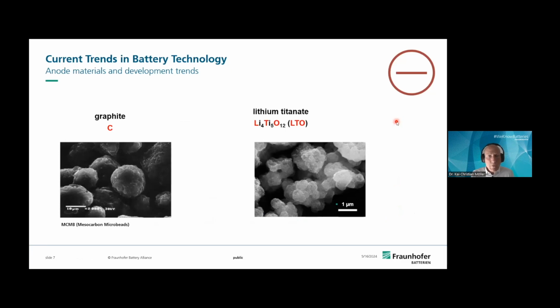If we have a look at the different morphology of the electrode materials, we have the state-of-the-art graphite powder, not in flakes as you would expect, but it's with high effort formed to so-called microbeads. You see the diameter is approximately 10 to 15 micrometers to make high-density electrodes. These materials are mixed with conductive additive and binder, and they are mixed with a solvent to get the slurry, and this liquid slurry is coated onto the current collectors.